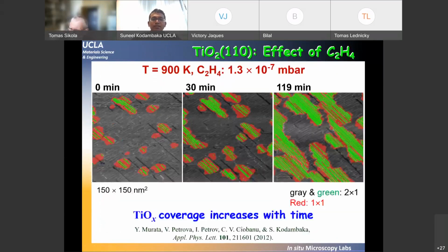Okay. And without going into lots of experimental details, I'll give you the highlight of these experiments. So these are time-lapsed images that are obtained while annealing the sample at about 900 Kelvin in presence of ethylene. And what we observe is that as time progresses, we see an increase in the growth of the stripe phase. Remember, the surface is TiO2, and we are exposing it to ethylene, but we are observing the growth of TiO2 structures, not carbides.